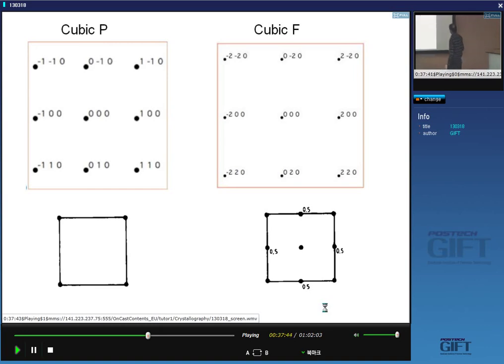Now, if I look at the 100 planes here, I've got another set of objects in the middle of the 100 planes, which will scatter X-rays or electrons exactly half a wavelength out of phase. So in this case, the 100 reflection will not appear for cubic F. It will have zero intensity. So my diffraction pattern here, where I had 100, will no longer have a 100. 200 are the planes with half the spacing of 100. There's nothing in between to scatter an antiphase wave, and therefore the reflection that I get is 200. 100 reflections are systematically absent if you have a cubic F lattice.